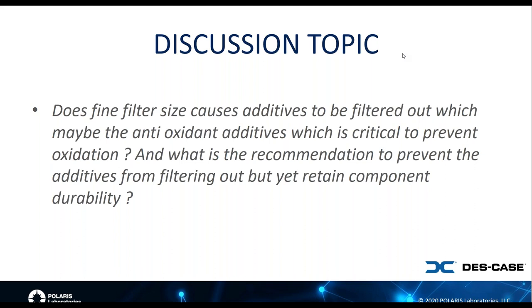And if the oil is at lower temperature, some of those additives are kind of on the edge of being in suspension of the oil and being dissolved within the oil. So I have seen circumstances where with certain gear oils, certain engine oils, more heavily additized oils at lower temperatures, you can remove some of those polymeric additives from the oil. The good news is that if you keep filtration above about 6 microns, the likelihood of that happening is fairly low. So with the likelihood of that happening being low, you're obviously in good condition.